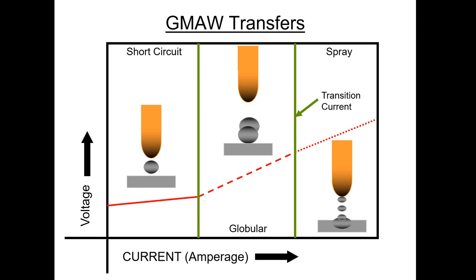I listen for a sputtering sound in every welding process I'm listening to for GMAW. There's a very distinctive and uncharacteristic sputtering sound that happens when there's a deposit of these large globules going to a base metal. Now, the globular transfer has its place, but it's not for welding steel to steel. It can be used with welding bronze commonly, where we don't want penetration or want very limited penetration. But globular transfer is not what we're looking for.